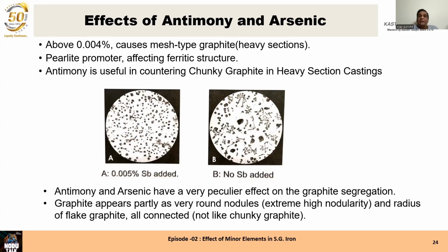Pearlite promoter affects ferritic structure. Antimony is useful in countering chunky graphite in heavy sections. So when you use antimony to avoid chunky graphite in heavy sections, you have to also use a little bit of cerium to compensate the bad effect of mesh graphite formation by antimony.